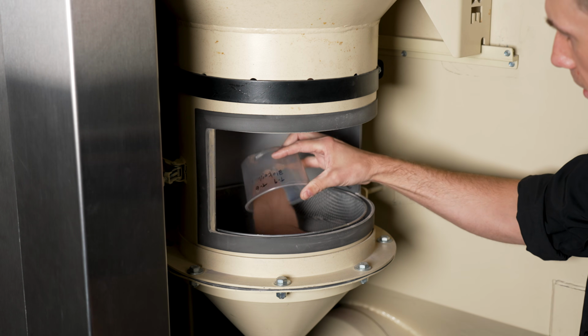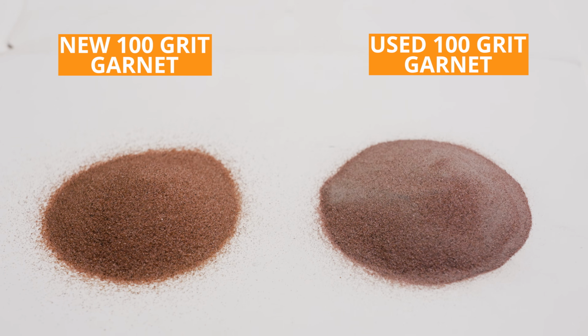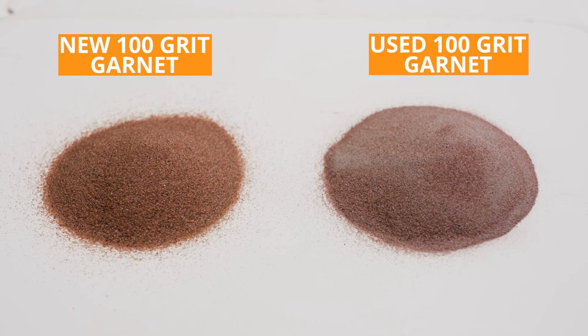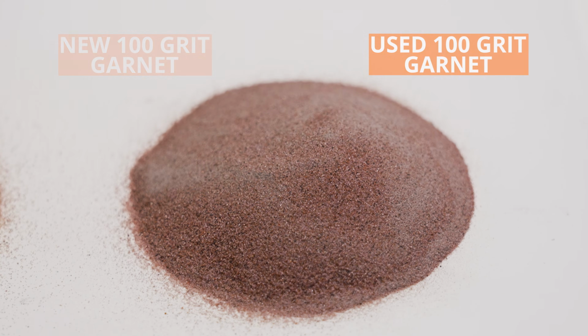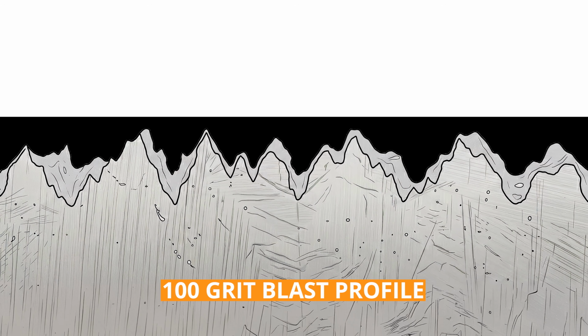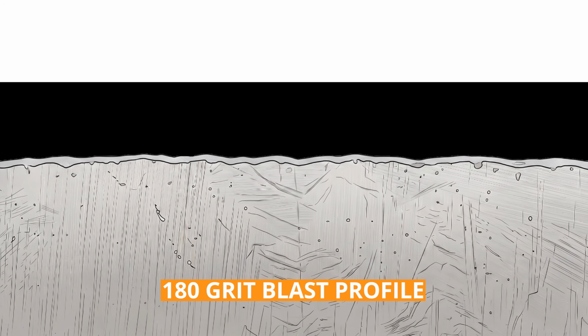When it comes to keeping up on your media, it's as simple as that. When you put brand new media into your blast cabinet and you blast for, let's say, a week, a couple weeks, a month, really depending on volume, that media is gonna start to break down over time. That 100 grit is gonna turn into 120. It's gonna turn into 180. Hopefully it doesn't turn into 220. Hopefully we're changing it out before then. But when it breaks down over time, that profile gets weaker, and we're still applying that 1 to 2 mils of Cerakote. So we're actually losing adhesion when the media starts to wear out.